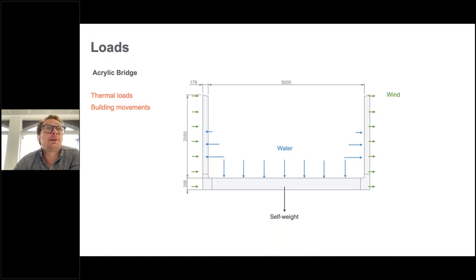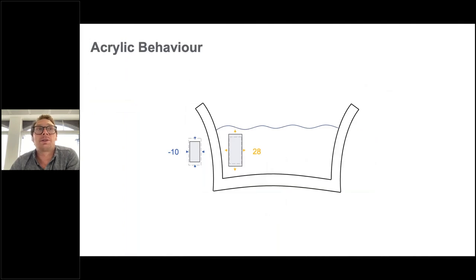And when combined with the dead load from the water, other aspects came in, for example, the thermal loads and building movements. As you can see, the hydrostatic pressure of the water and the wind load acting on the side of the tub, blowing it horizontally in between. But the thermal behavior was a little bit more problematic. So if we've got freezing temperatures in London and the water is consistent all year round, we have this temperature differential happening across the surface.